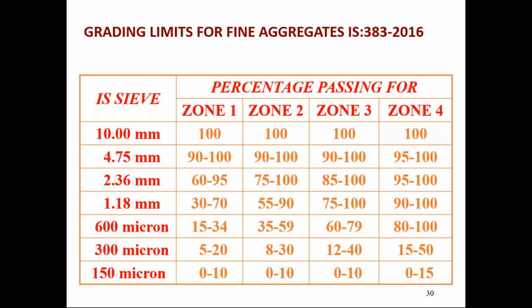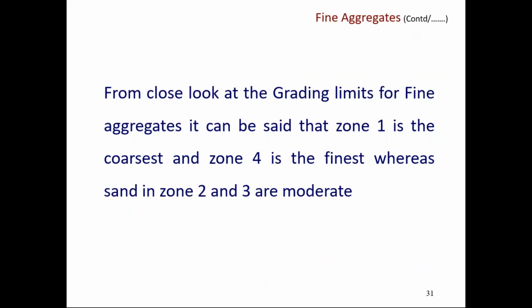Percentage passing through 600 micron is the critical parameter. From a close look at the grading limits of fine aggregates, it can be seen that zone 1 is the coarsest and zone 4 is the finest. Zone 2 and zone 3 are the moderate zones. So we prefer to have fine aggregate in the concrete conforming to zone 2 and zone 3. Zone 1 can be used, the only thing is it is coarse in nature. We need to increase the percentage of sand when we want to use zone 1 sand.